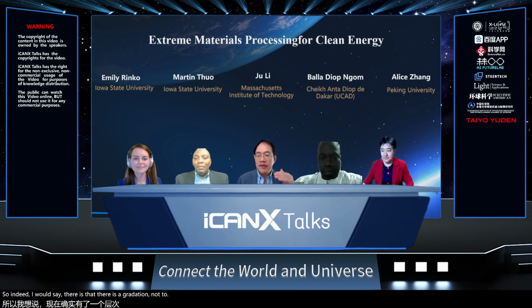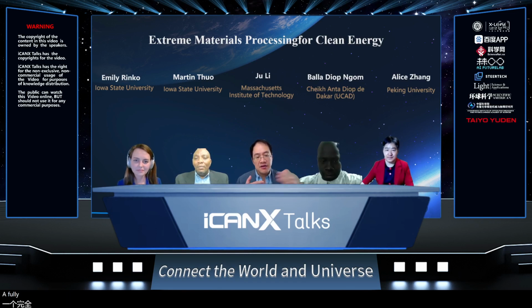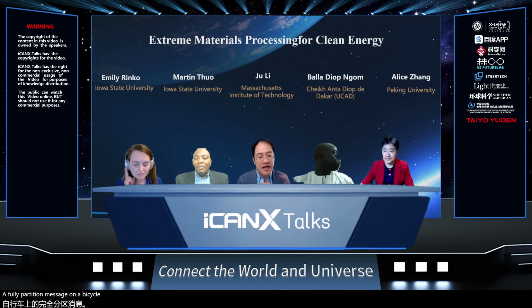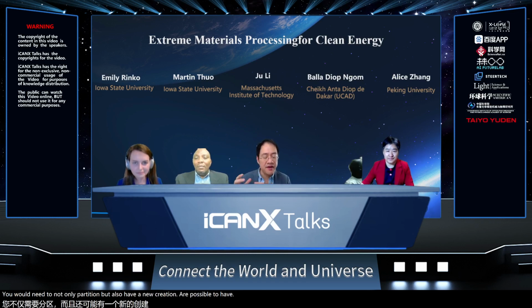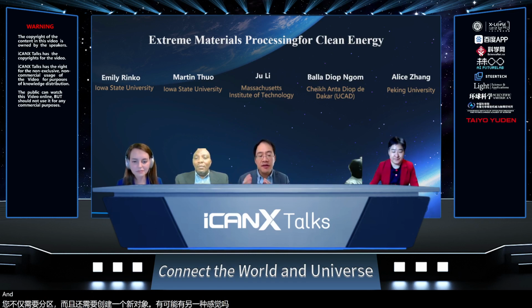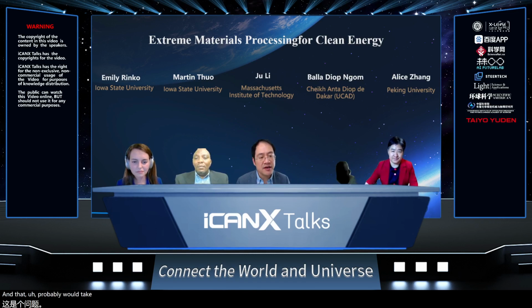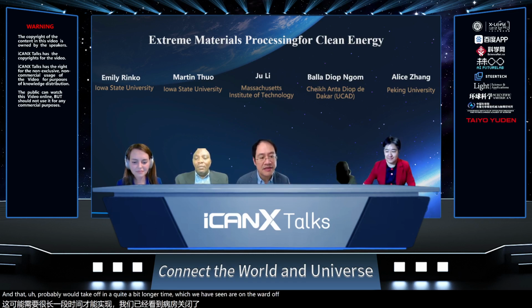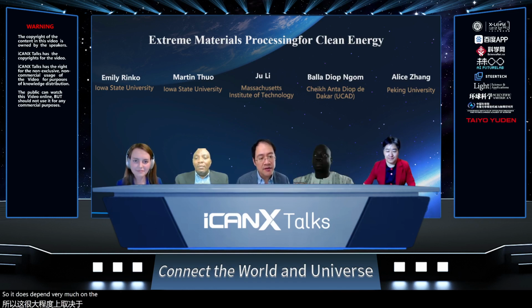Now, to have a fully partitioned, let's say a biphasic, a Janus particle, you would need to not only partition but also have a nucleation process to have another phase, and that probably would take quite a bit longer time, which we have seen on the order of maybe seconds to do that. So it does depend very much on the cooling rate in this time temperature transformation TTT diagram.